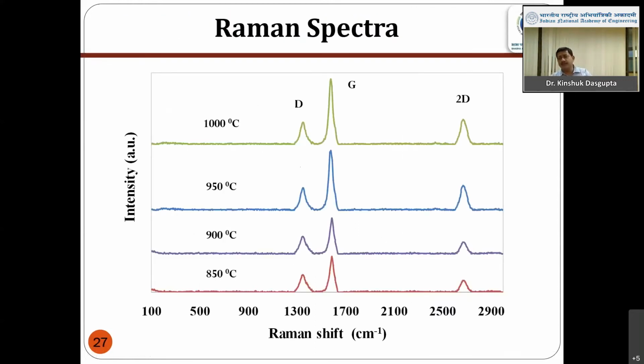Now after we get the nanotube, we need to characterize it. Can I say the product is carbon nanotube, or is it amorphous carbon or other forms of carbon? We can see under a microscope, but that takes time because you require sample preparation. So as the first step, let us look at Raman spectra. Raman spectroscopy is a method by which you can characterize your product very quickly, and you can take samples from a large number of positions and see their Raman spectra, which is a very quick technique.